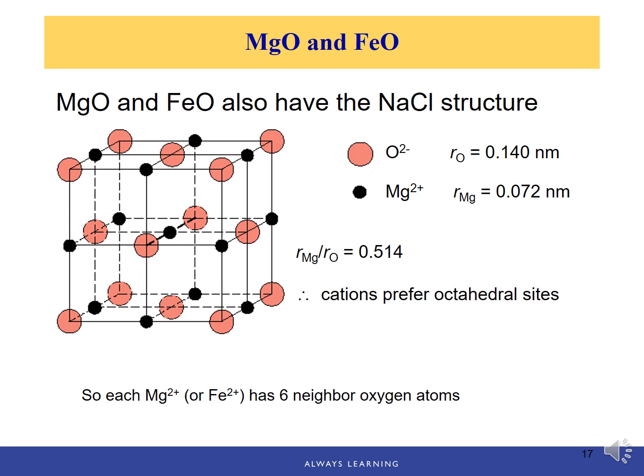With the same characteristic, we can also figure out that magnesium oxide and iron oxide also have the rock salt structure. Based on the ratio of RC over RA, we have the ratio is 0.514. Therefore, the coordination number must be 6, so the cations prefer the octahedral sites. And this coordination number is true for both. There are 6 cations surrounding each anion, and there are 6 anions surrounding each cation.